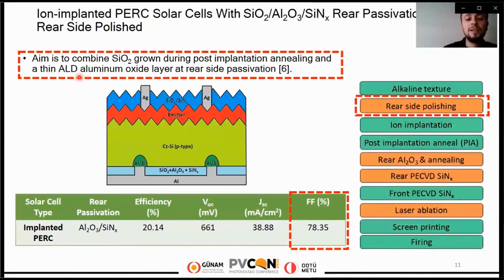This is another impressive implanted PERC cell study conducted by Canadian Solar, and they reported more than 20% conversion efficiency. Their aim was to combine silicon dioxide grown during the post-implantation annealing and a thin ALD alumina layer at the rear side. But they also included a rear side polishing step here, because from the previous slide we know that the surface morphology is very effective in determining the silicon dioxide passivation quality at the rear side. When you look at their fill factor values, it is also not very high as in the previous case. This can also be due to the thick silicon dioxide layer at the front side.